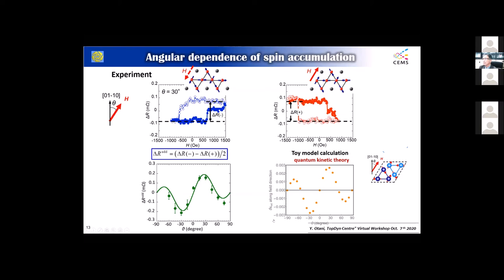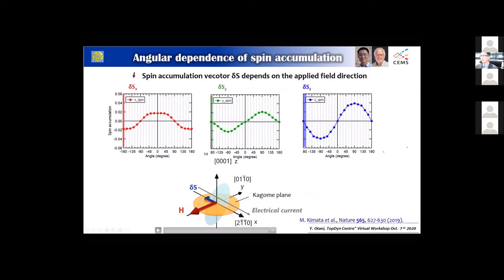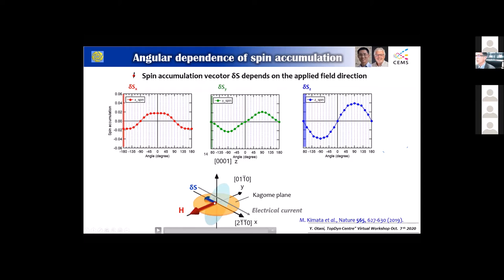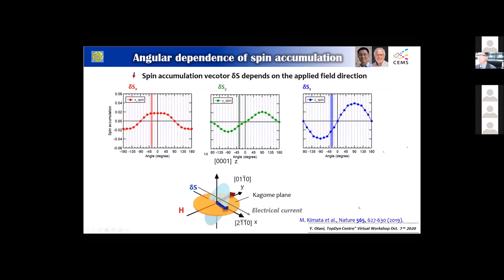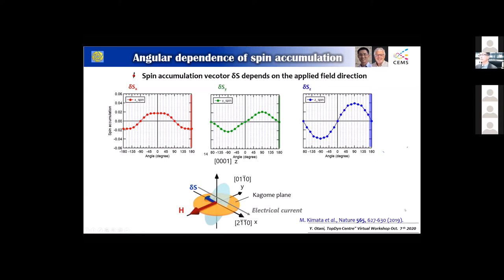The calculated results show in-plane components Sx and Sy, as well as the out-of-plane Z-component. Surprisingly, there is an out-of-plane component in the spin density. Also interestingly, if we rotate the spin structure, the spin accumulation component also changes accordingly. The spin density vector rotates with the rotation of the external magnetic field within a light blue circle — that is a characteristic of this magnetic spin Hall effect.